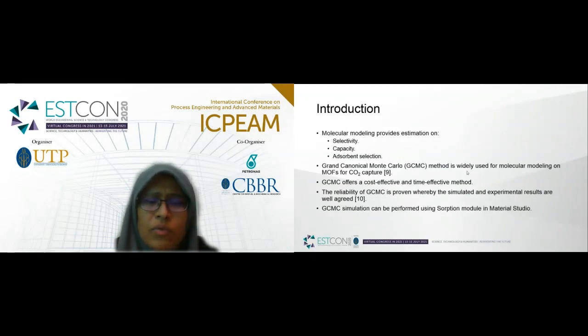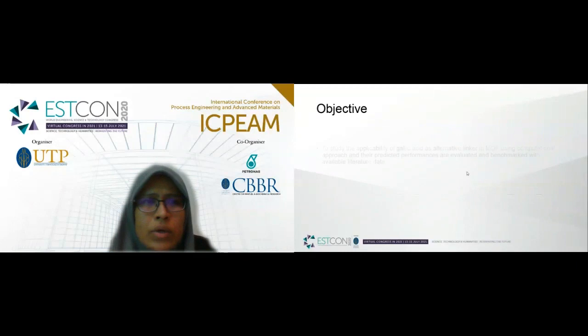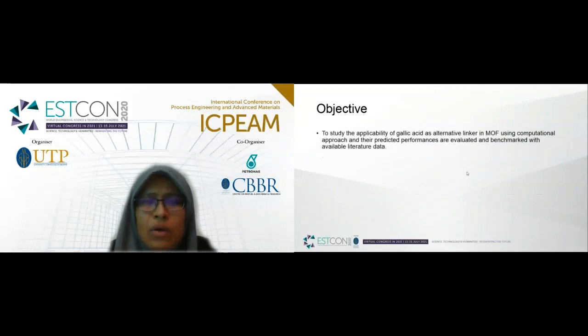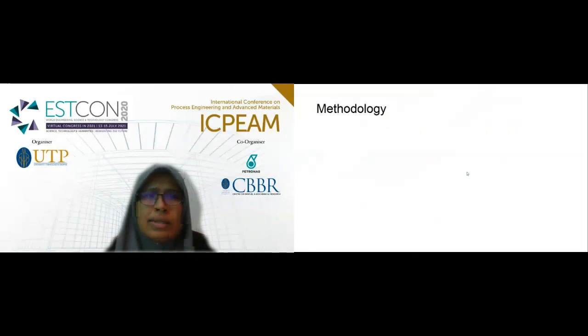GCMC simulation can be performed using the sorption module in Material Studio in order to compute a loading curve for molecules on MOF. This work is to study the applicability of gallic acid as an alternative linker in MOF using a computational approach, and their predicted performance is evaluated and benchmarked with available literature data. Next is the methodology.